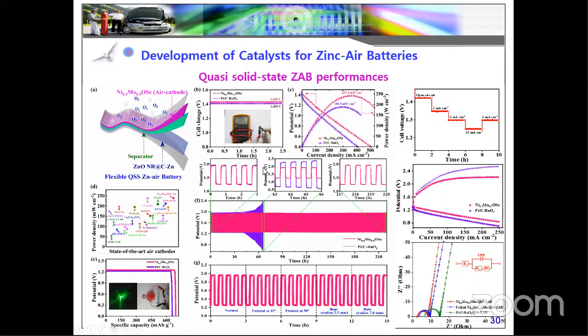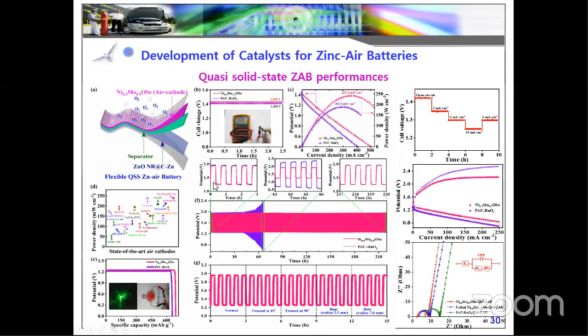This part is fully the OER part. Suppose your catalyst is not active in OER, the potential goes higher because it is not maintained. But suppose your material is not stable in the ORR part, it may come down because the potential will vary. You can see our material is almost stable for 200 hours.